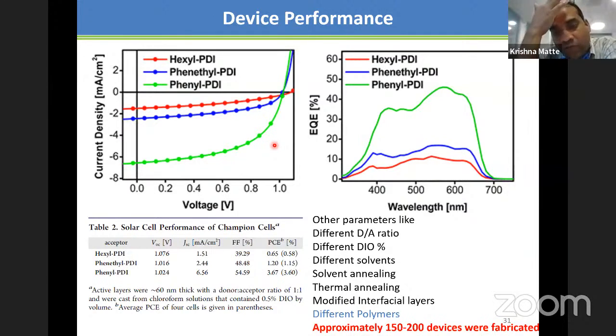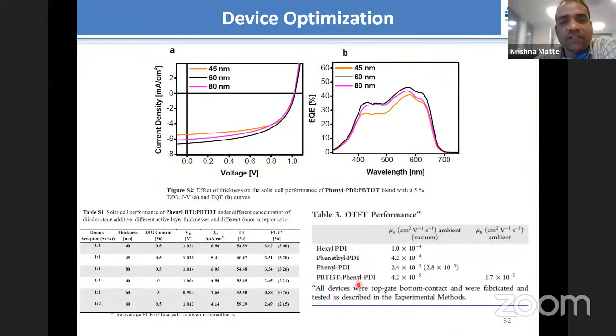After that, we fabricated various devices, and the efficiency of them is around 3.67%. As I said, though the efficiencies are not high, these materials are really cheap. So for getting these efficiencies, one needs to optimize various parameters like donor acceptors, different solvents, thermal annealing, interfacial layers. Then you'll end up with one good optimized structure to fabricate these solar cells.